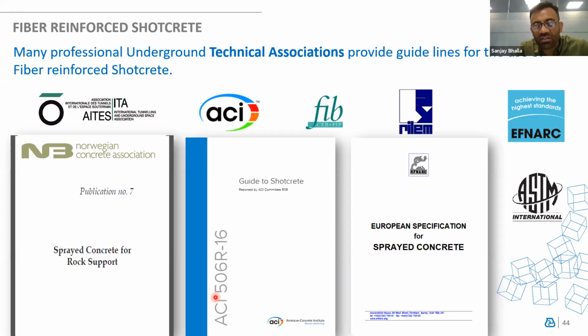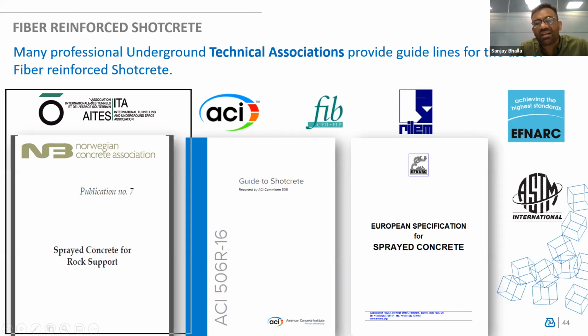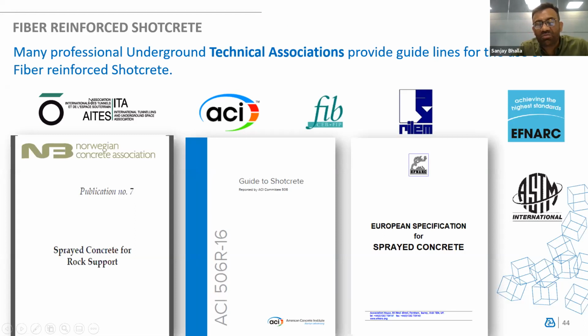I just would like to add to this also, since we have been involved with a lot of additives in India at various sites, the same additive may work very well in a region in the north and may not work in a similar mix design in the south. Because what Davide said, it all depends upon the clinkers, the source of the cement, and where the aggregate is coming from. So sometimes we have to modify the additive as per the local mix design. Generally, in a technical data sheet, we mention the dosage limitations, like from 0.5 to 1% or 1.2%. But it can vary, maybe plus or minus 2-3% also, depending upon the temperature and the aggregate condition.